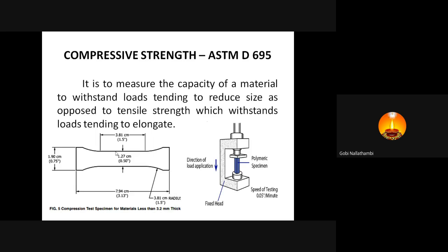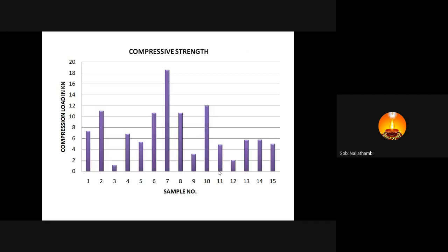Okay, so then again, compressive strength. There is a different unit here, that is the top plate and bottom plate. Between these, the sample is placed, then the compressive force is applied, and the force withstood by the specimen can be measured. With this, sample 7 is giving very high compressive strength. But in the case of samples 13, 14, and 15, it is almost 1/4 of sample 7.